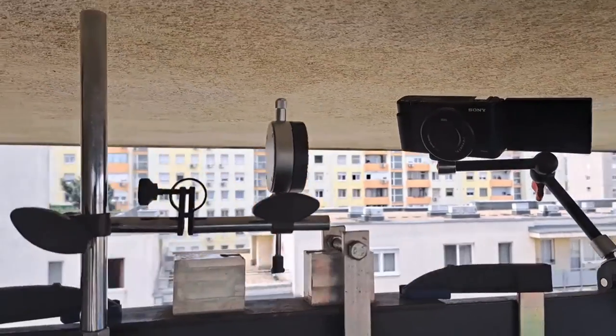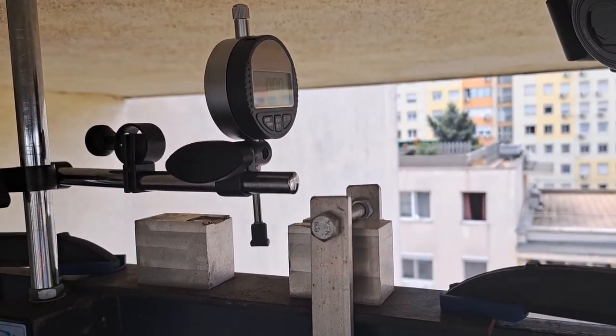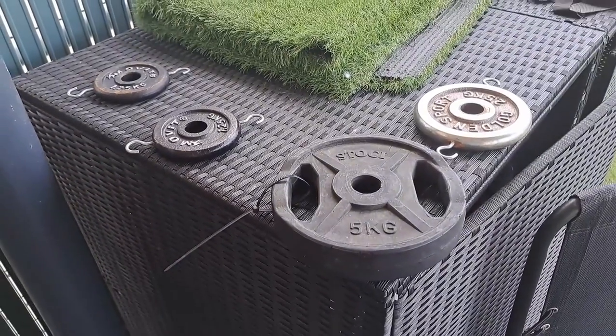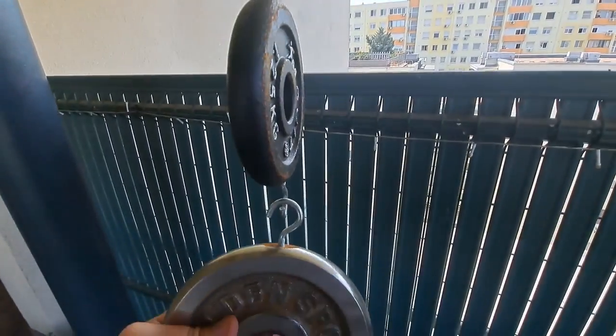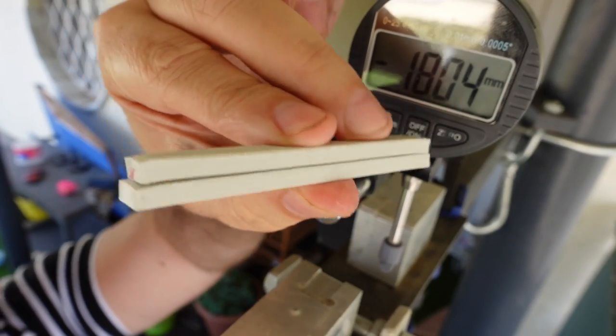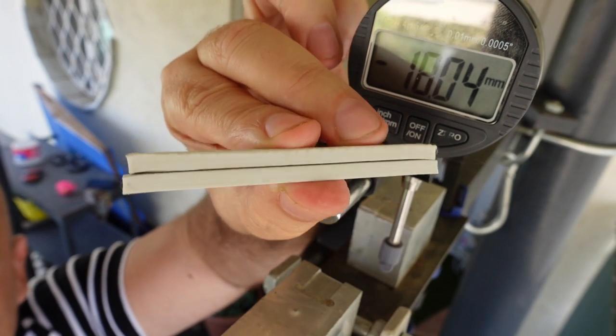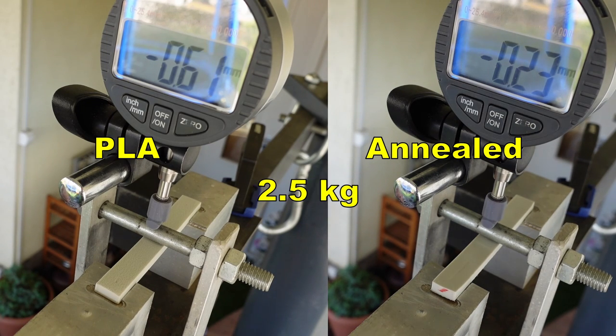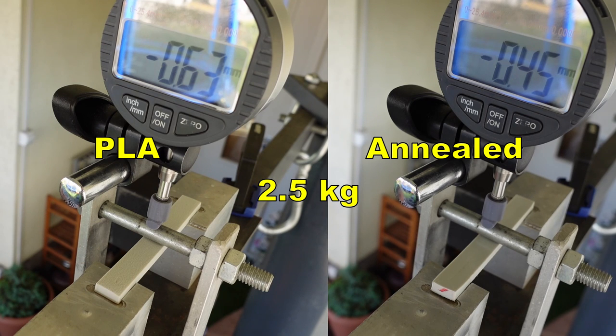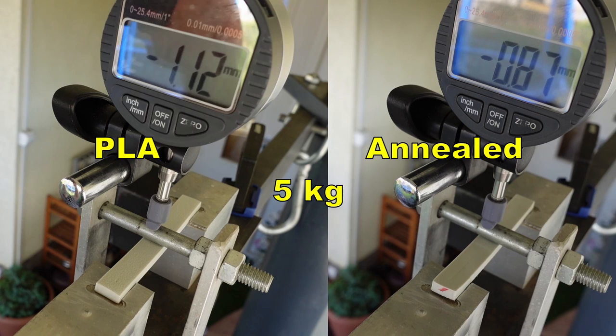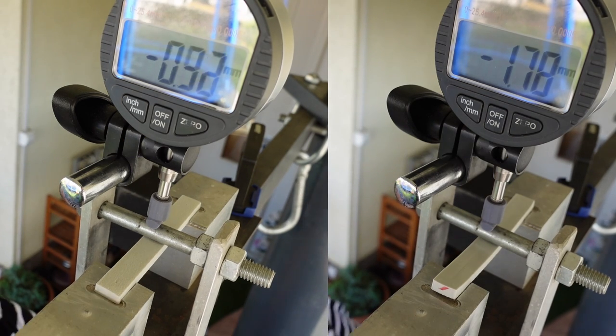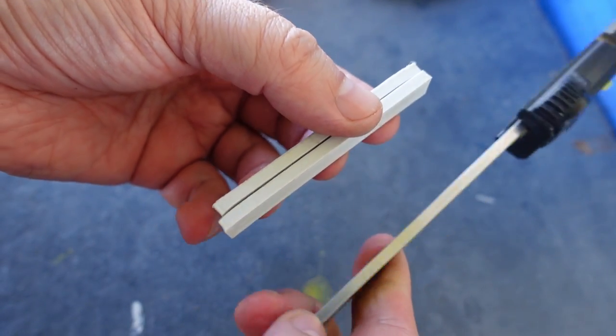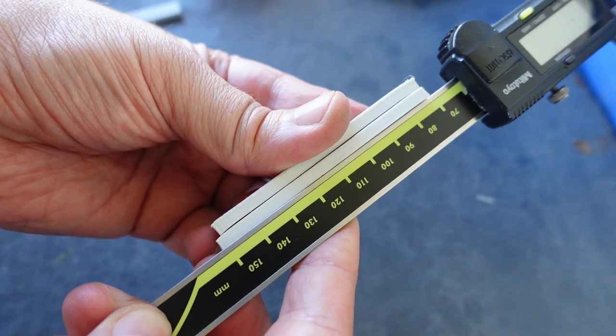Three point bending test. Distance between supports is 15 millimeters. And now I will place this load one by one, and I will measure the deformation after 30 and 60 seconds. Here you can see the annealed version is a little bit shorter because of that shrinking. And this is the deformation under 1.25 kilograms, 2.5 kilograms, 5 kilograms, 10 kilograms and now remove the load. And basically I cannot see any visual deformation on them after this test.